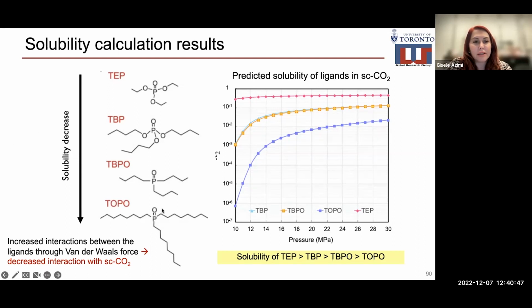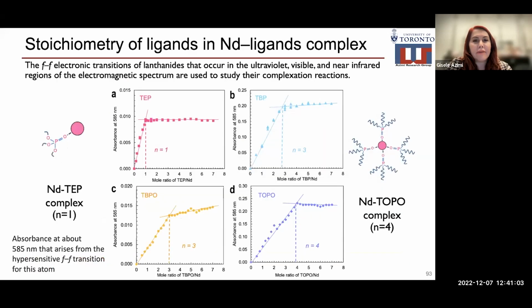If we look at the molecular structure of these 4, we see that the solubility decreases from TEP to TOPO, and that is due to the increased interaction between the ligands through van der Waals forces, which decreases the interactions with supercritical CO2. We also determined the stoichiometry of the ligand in neodymium ligand complex using UV-Vis. Here we made solutions of neodymium nitrate, and we added a predetermined amount of the ligand, for example, TEP or TBP, to that, and we measured the absorbance of the complex at 585 nanometer.